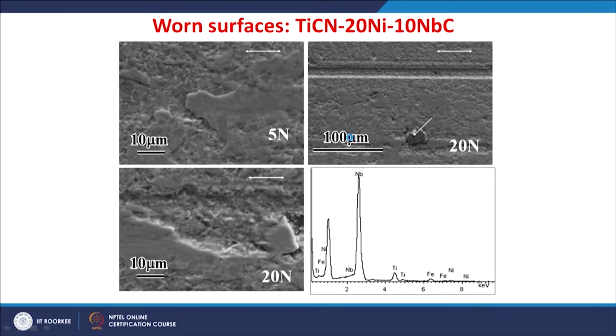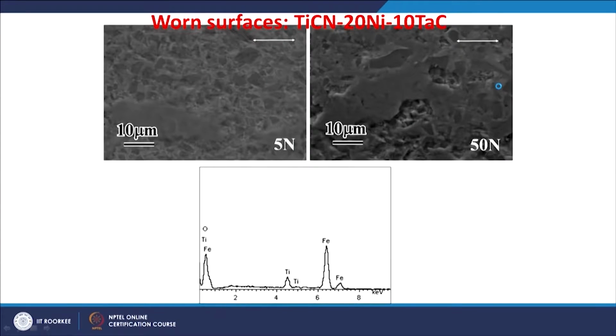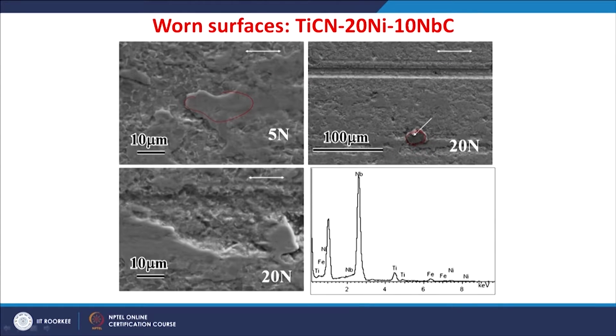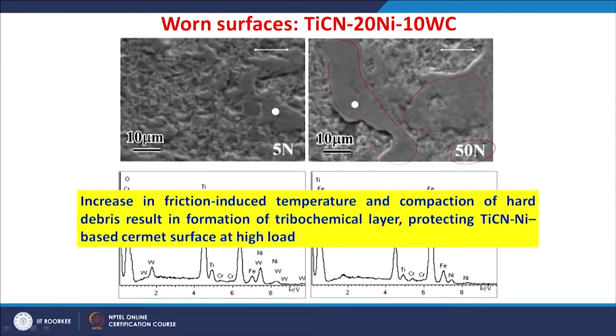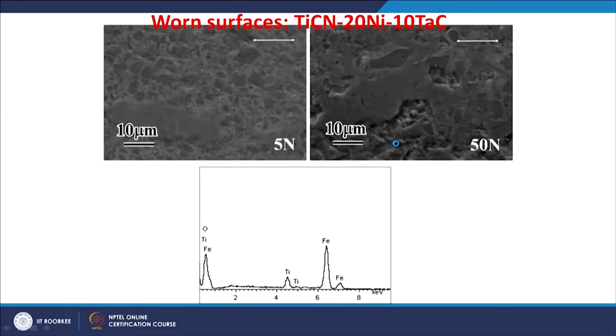You can again see there is a pull out of this material and the signatures of the tribolayer, and also the entrapment of the debris on the layer along with these abraded grooves. So, more or less similar features are observed, but in all these conditions the nickel presence is very minimal on the tribolayer. So, these are the worn surfaces obtained for the cermet after sliding at 5 and 50 Newton.